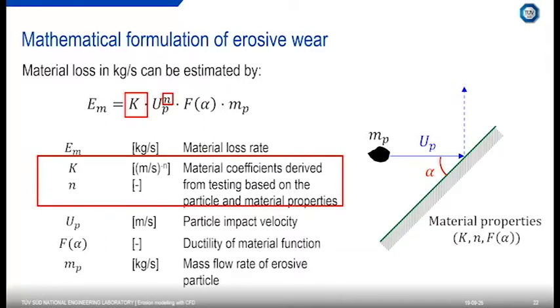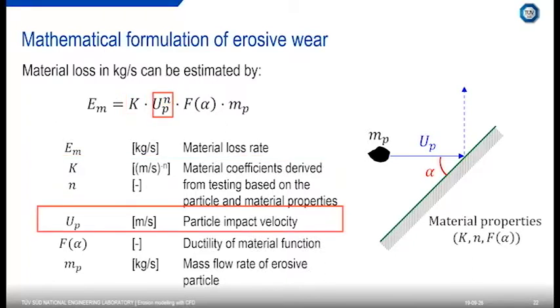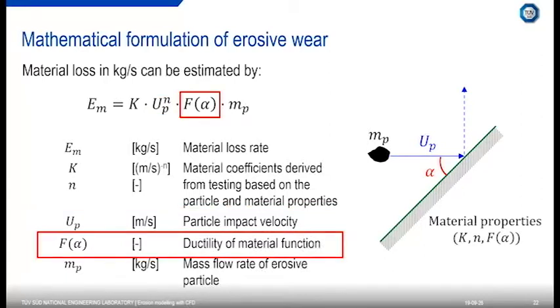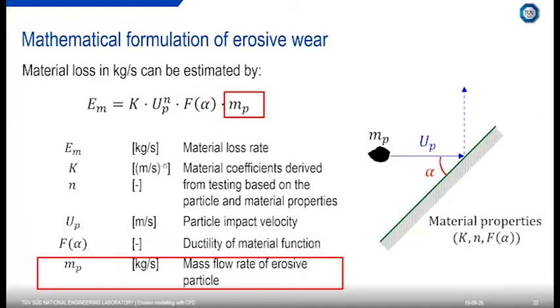So here, typically K and n, these are derived from testing, and they're based on both the particle and the material properties. The particle impact velocity, typically that's quite difficult to measure. So you may know the fluid velocity, and you then may have to use computational fluid dynamics to work out actually what the impact velocity is. We then also want to know our ductility of our material, F of alpha, and of course our mass flow rate of our particles.